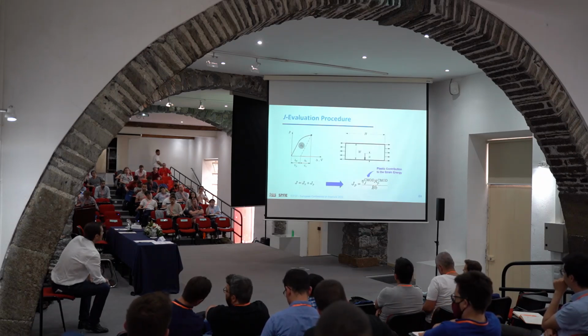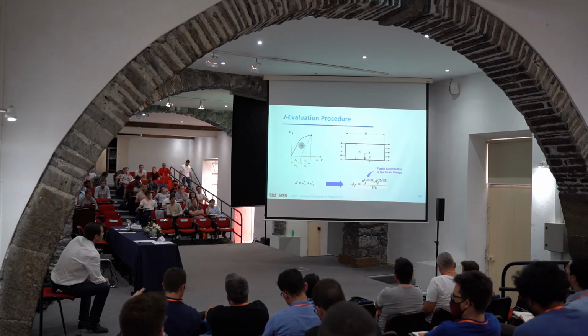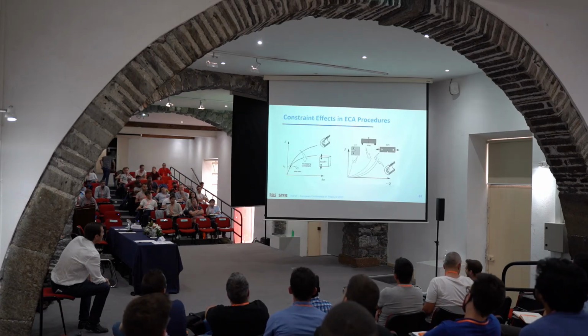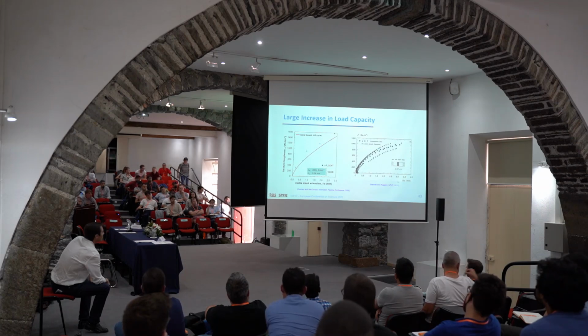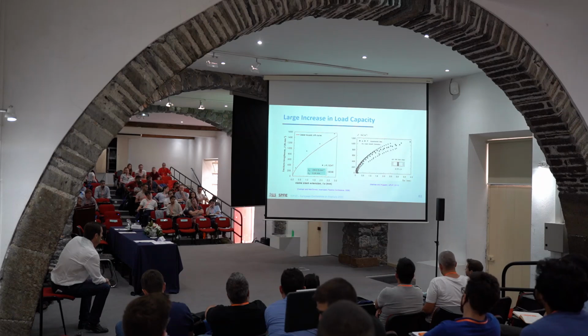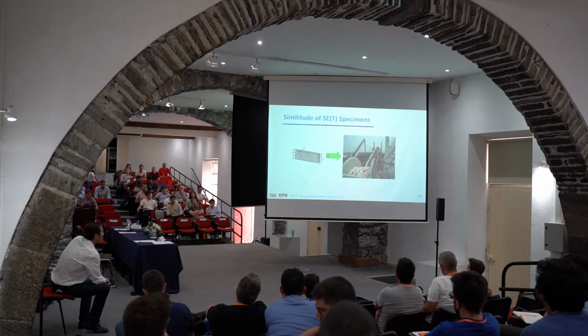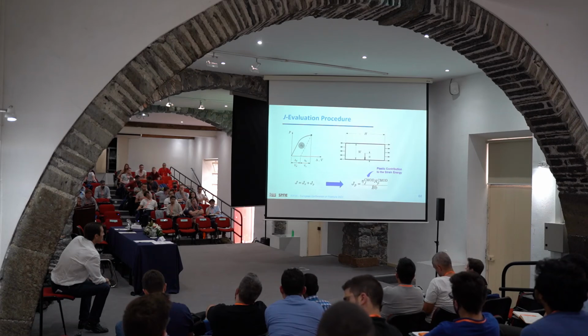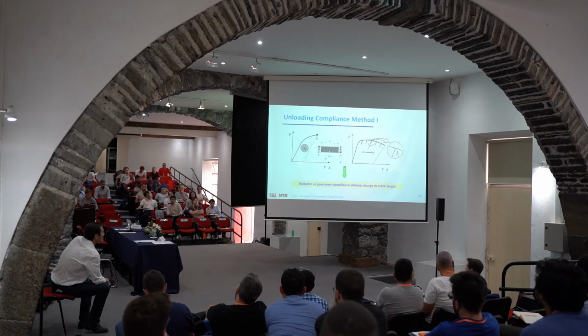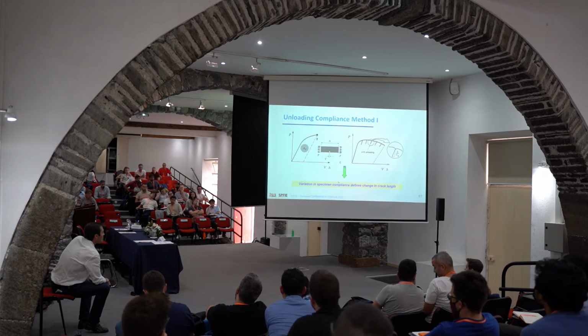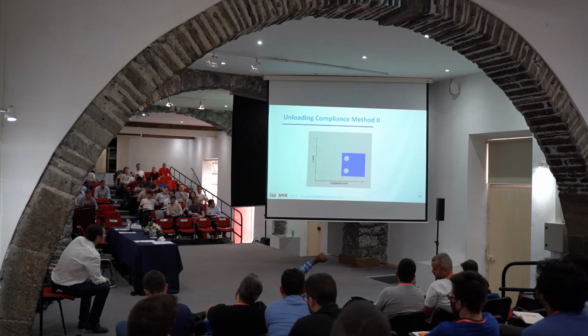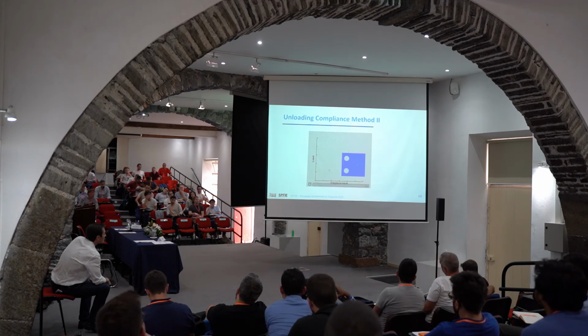What we need to do is to evaluate the resistance curve, this curve here, for the assessment. So how do we evaluate this? This is a very simple procedure which relies on the variation of the specimen compliance. We don't put a camera there, or sometimes a high resolution camera. Here we just measure the variation of the compliance, which is like this. We load, unload.